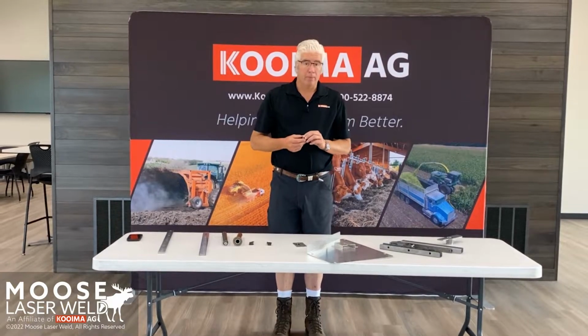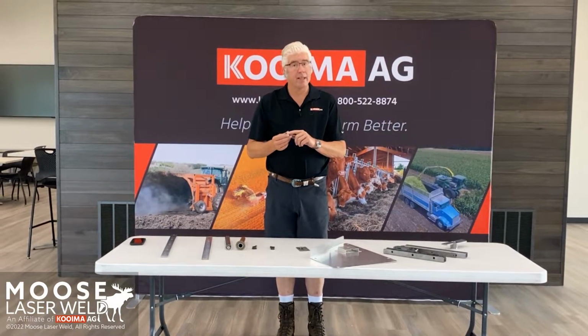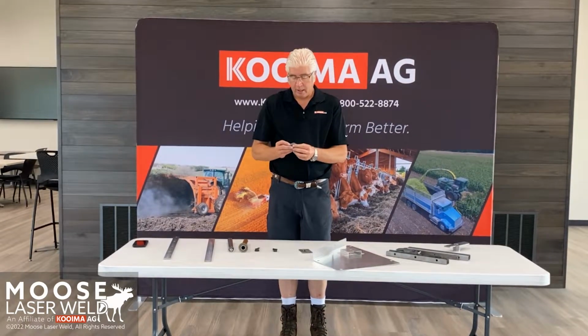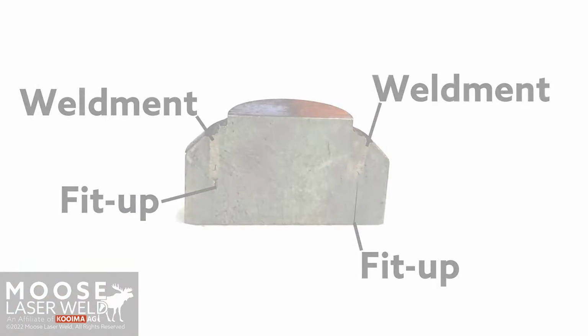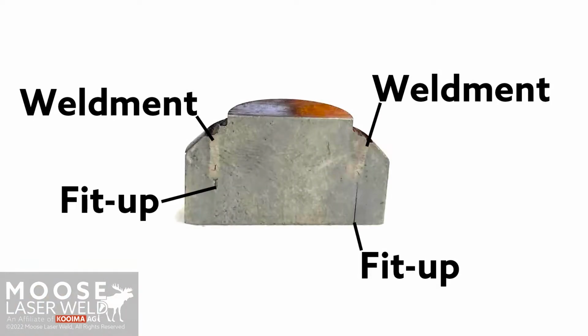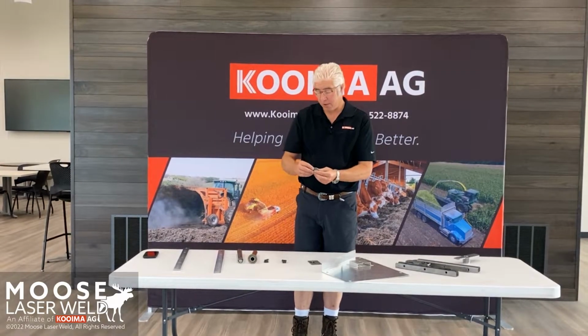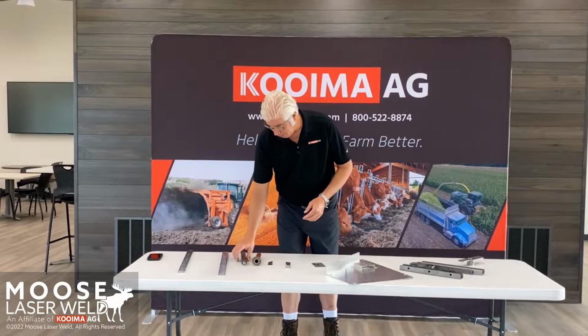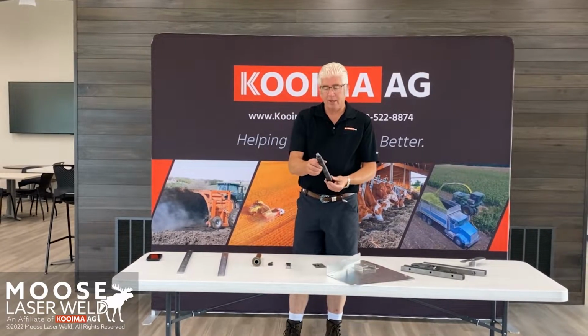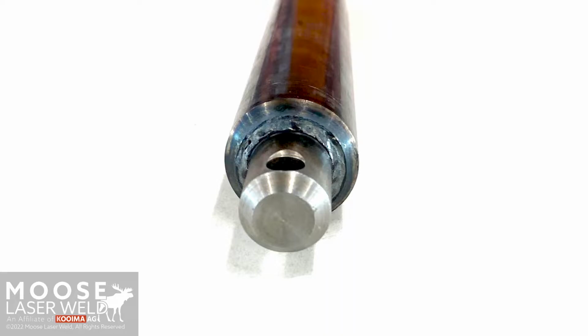The proper fit up gives us a very nice, deep, full penetration weld. You can see here, the fit up produces a nice deep weld. We're getting about 3 millimeters of depth penetration. And that is the sub part from this pin weldment where we weld full penetration all the way around.